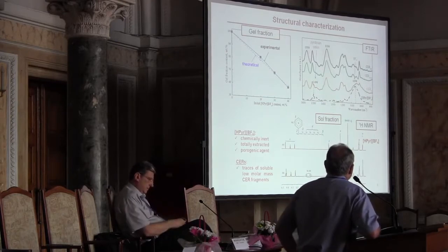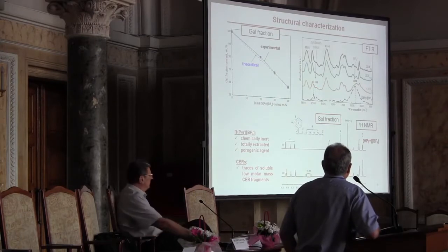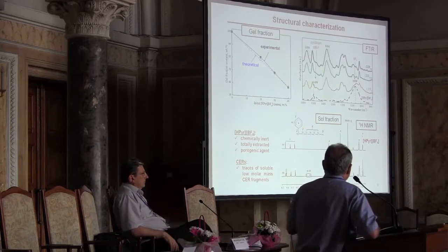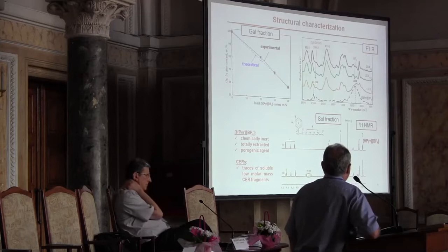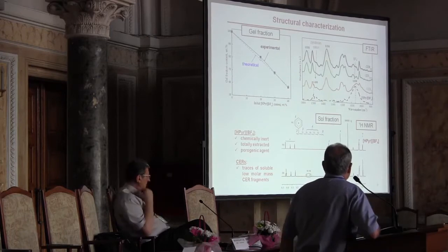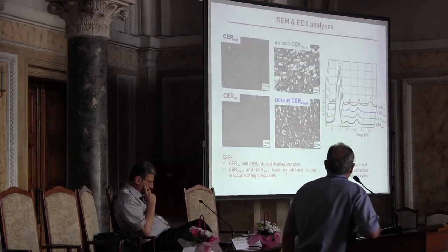Also in FTIR spectra, you can see that ionic liquid is removed, no traces of ionic liquid in the gel fraction. And in the sol fraction, we can find ionic liquid and some traces of cyanate ester which was not grafted to the network.